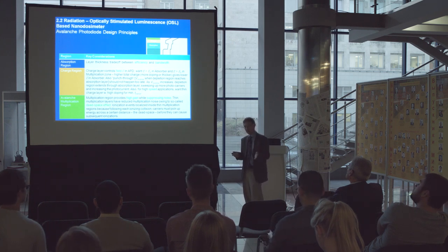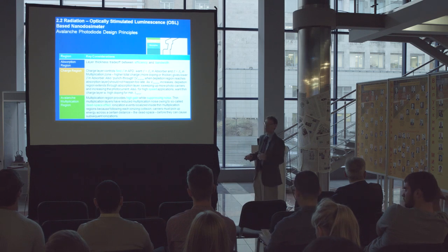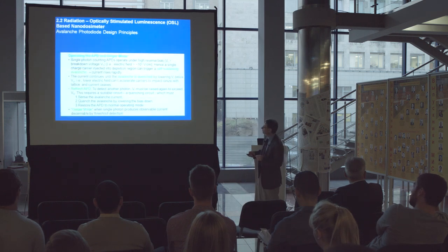And then in the avalanche region, this is the piece at the back here, the key aspect will be, of course, we can get this avalanche, but the noise matters. If I'm looking at electrons, I don't want holes to be created at the same time, or really all my gain goes away, because I've got one current going this way and one that way, which is nothing. So I want to have a unipolar, one carrier, essentially dictating that. So the relative efficiency of that, the dead space concerns, all of those are important.